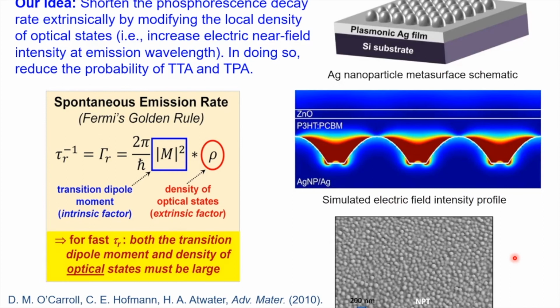So we're transferring this idea to the metasurface. We can get these local hotspots or local electric field enhancements in nanoparticle-based metasurfaces. They're also nice in that they can be readily integrated into a device because they're planar, extended in two dimensions, whereas they're very thin in the third dimension. So they're very useful for thin film optoelectronics. And you can see here from a simulated electromagnetic field profile, you can get very intense electric fields between the particles when the right size and interparticle spacing is chosen for the metasurface.